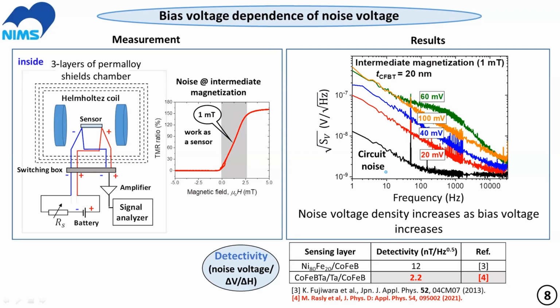And we started to increase the bias voltage. And as you can see here, normally as we increase the bias voltage, the noise voltage increases. And from this measurement, we picked the value of the noise voltage for 30 millivolts, and we calculated the magnetic field detectivity. We got 2.2 nanotesla per root hertz, which is much better than that reported for the magnetic sensor developed with a nickel iron or cobalt iron boron free layer.